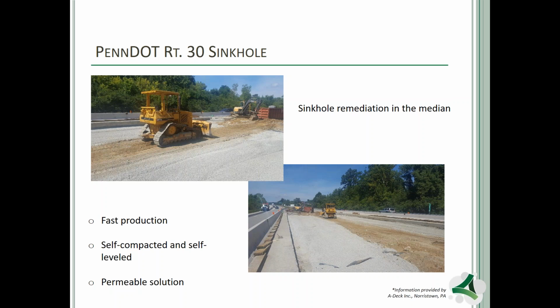In between lifts of cellular concrete, all we need is 1 PSI. We do the walkability test and we can put another lift. It generally occurs between 6 to 12 hours after the placement of a lift to place another one, and that is without an accelerant. Use an accelerant, that'll speed it up a little bit.